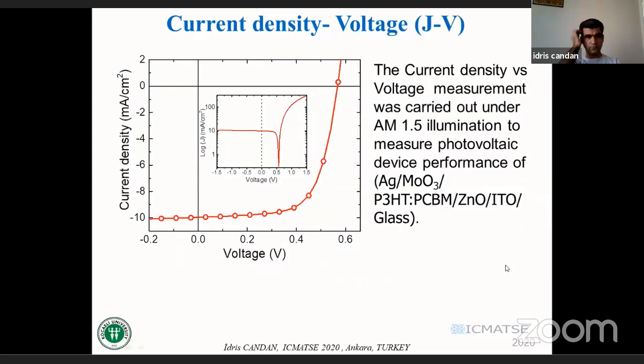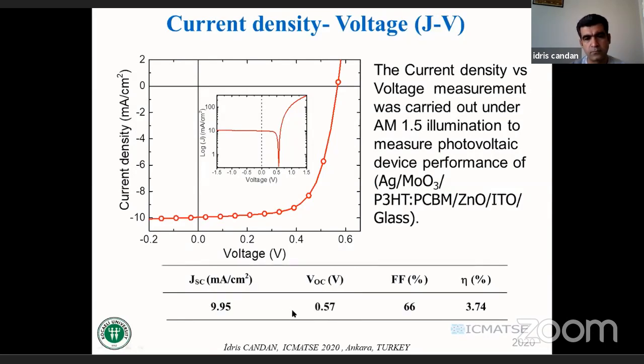And when we look at the solar performance of our devices, the current density and voltage measurement was carried out under the AM1.5 illumination to measure the photovoltaic performance, with this device configuration. And we see that our power conversion efficiency is around 3.74% and fill factor 66%, and open circuit voltage is 0.57 volt, and short circuit current is 9.95 milliampere per centimeter square.